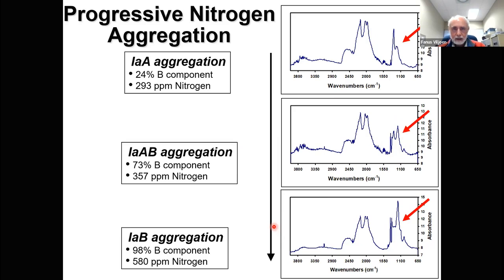And then finally, a highly aggregated stone, which contains virtually all of its nitrogen in the IaB aggregation. This stone contains 98% of its nitrogen in the highly aggregated B state. This stone contains 600 ppm nitrogen. And you can now see that this peak is very pronounced. So for all intents and purposes, the height of these peaks corresponds to nitrogen content, and the shape of these peaks corresponds to nitrogen aggregation state, as you can see here. That being poorly aggregated and this being highly aggregated nitrogen.